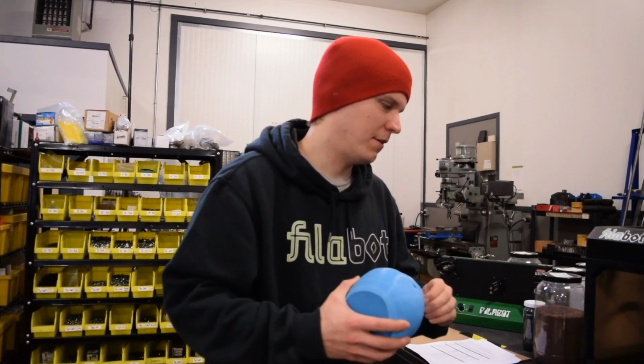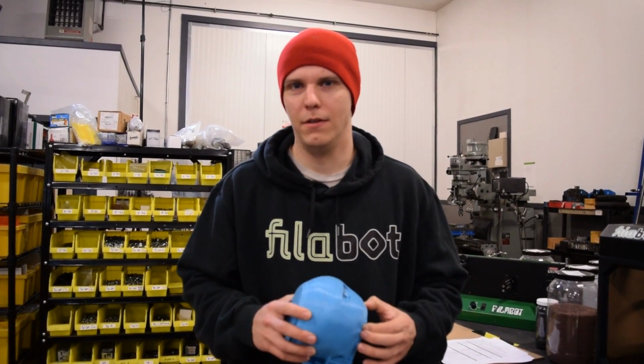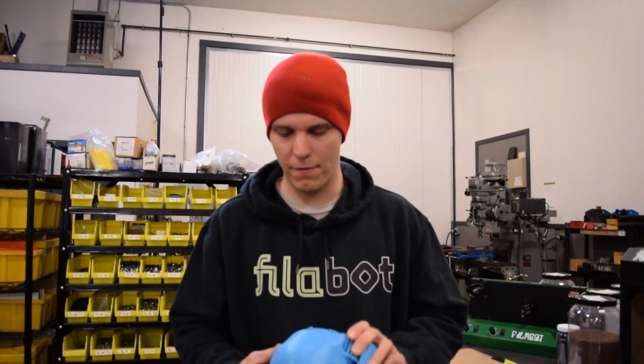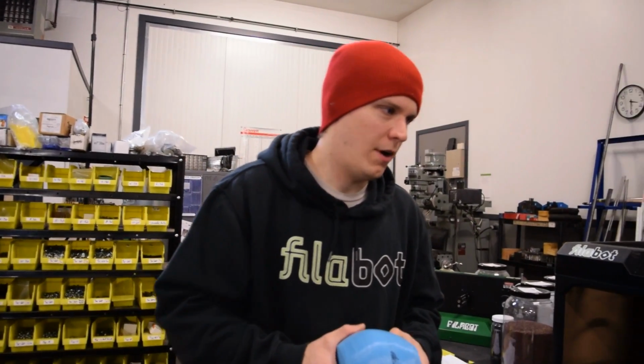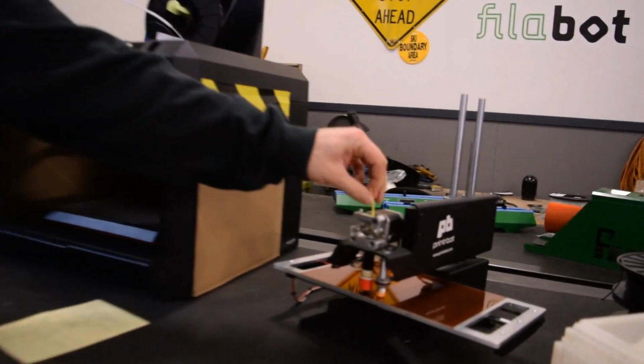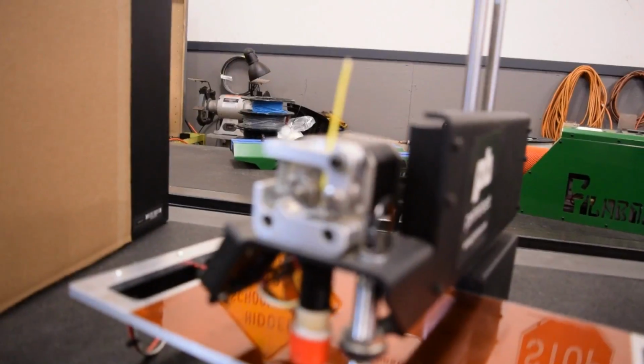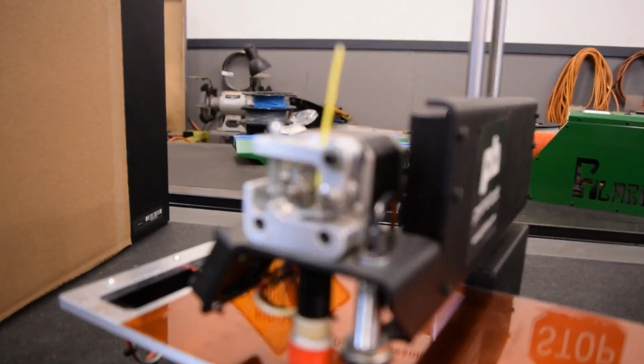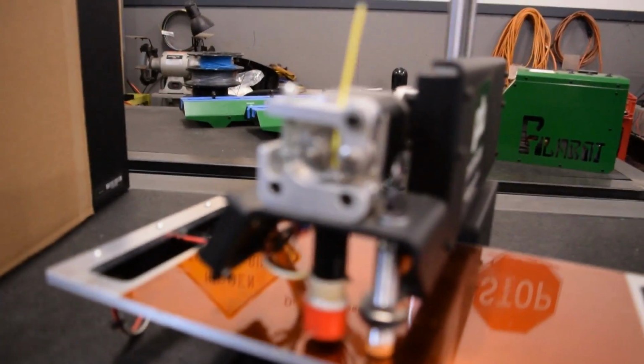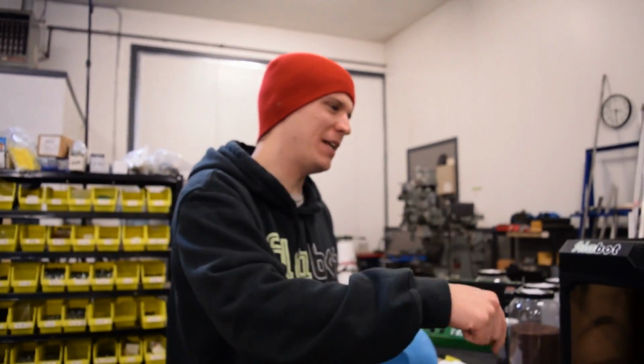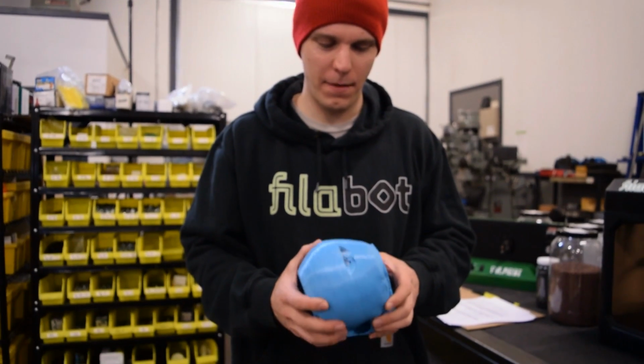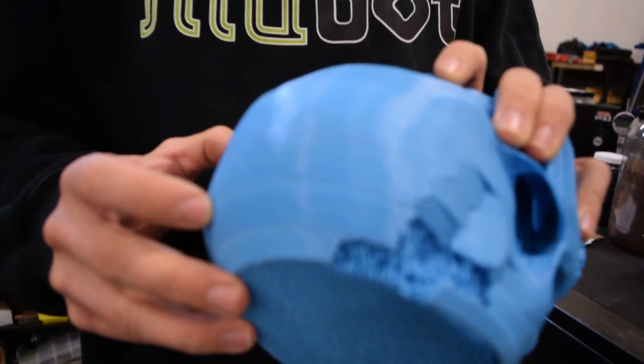So filament diameter tolerance is the main issue that we focus on with Filabots, on top of melt filters and just the general properties of the polymer, like the softness and how easy it is to extrude. But diameter tolerance is the main one. A very obvious problem you might have is if your filament's too big to actually fit inside your extruder, it's going to stop. But the other issue is if it gets too thin, it could break.